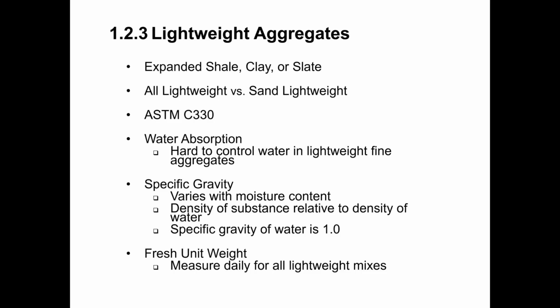One of the key complicating factors when using a lightweight aggregate is the water absorption. For a regular weight aggregate, you may be looking at an absorption of 1 to 2%, somewhere in that range, just depending on the density of the aggregate. But for a lightweight aggregate, you may be looking at a water absorption of 25 to 30%. It's significantly higher. It's a multiple higher. And so because the water content of the aggregate can vary so widely, it really complicates the batching process because we're not able to achieve the same level of consistency with moisture content that we are with a regular weight aggregate.